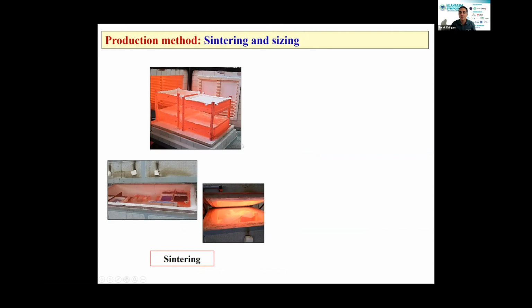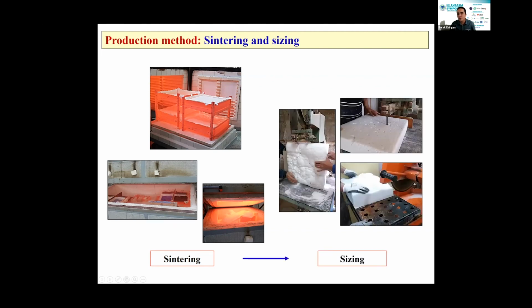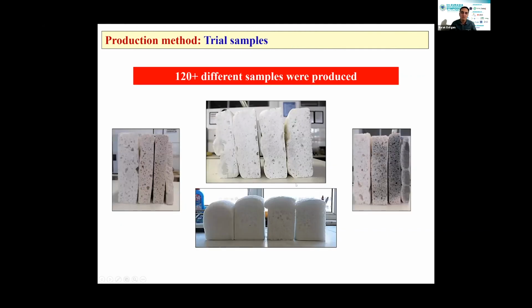As you know, sintering is the other name of heat application. We tried 10 different heat processing diagrams inside different types of ovens. After completion of forming up to the required thickness, the sizing stage starts. We use different types of saws to size our original members. In total, we produced more than 120 different samples, but many of them are not effective, as you see here. These elements have too low a density value, or their thickness is not enough for the forming application.